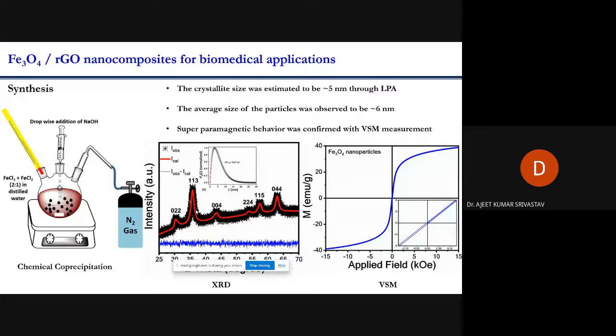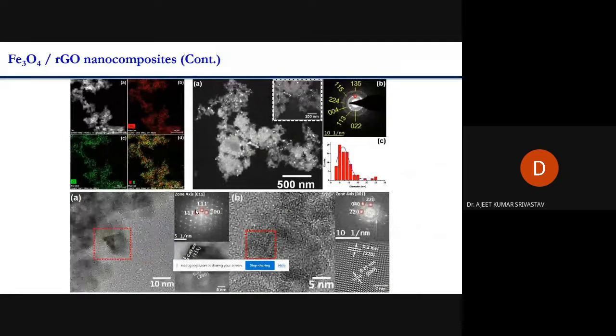And there is superparamagnetic behavior of the particles. If you see the right bottom, from the hysteresis loop we got almost a closed loop, which shows the superparamagnetic behavior of the magnetite nanoparticles. This is the elemental mapping for the magnetite nanoparticles, and you can see dark field imaging where you can see the individual particles.